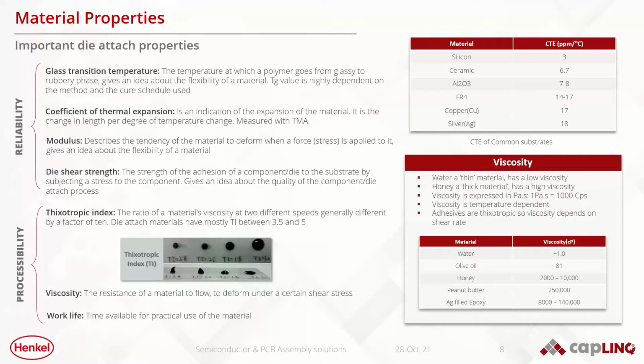The main material properties when you're talking about a die attach material can be split into two broad categories. The first category is the reliability. And there we're talking about glass transition temperature, coefficient of thermal expansion, CTE, the modulus of the material, and the die shear strength. If we take a look at common materials such as the silicon die itself, with a CTE of 3, or ceramic or the FR4 in a laminate substrate, or even lead frames that might have a CTE of 17 or 18. Oftentimes engineers want to have the lowest possible CTE for their die attach, when in fact what they should be looking for is the CTE that best matches the die and the substrate to which it's being attached.